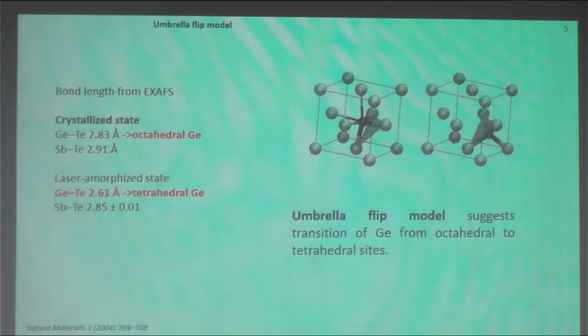So what is happening here? We have the crystalline phase, and on phase change between the crystalline and amorphous state, the octahedral germanium shifts to the tetrahedral sites. It brings high distortions in the system, and the system collapses and transforms to the amorphous state. So it's based on the transition between octahedral and tetrahedral sites.